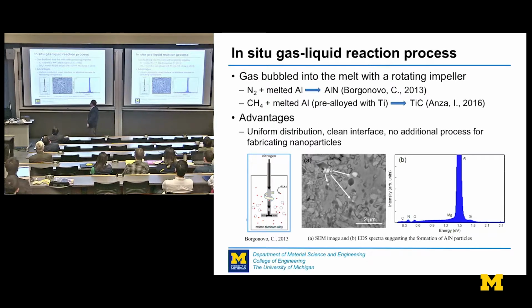And so, and we don't take credit for this, it came from Worcester Poly, Diran Apelian there: wait a second, can't we form the particles in situ in the melt? So they start off naturally dispersed. They came up with the idea of bubbling nitrogen through the molten aluminum. It reacts in situ and forms aluminum nitride particles, and they are of the size we want. They then showed they can bubble methane, or actually CO2, into an aluminum alloyed with a little titanium and form titanium carbide. So we now have a way that worked at lab scale to produce nanoparticle reinforced aluminum.